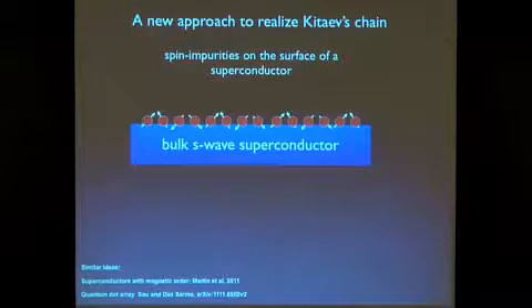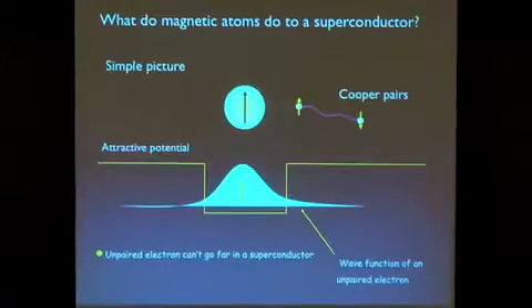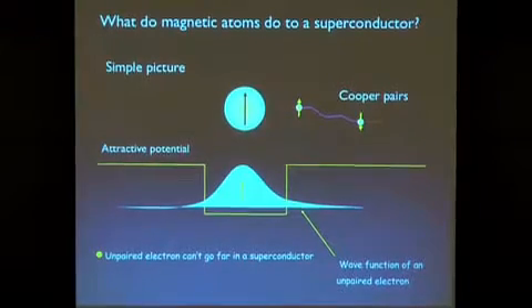As I will show you, in the modeling we have done, this actually shows to be a very promising route. So before I do that, let me just describe to you what an impurity does to a superconductor. If I have a magnetic impurity, that's when things happen. Non-magnetic impurities don't do anything to an S-wave superconductor. A magnetic one, simply put, attracts one of the spins. It breaks Cooper pairs. So you can think of this as sort of an attractive potential for one of the pairs.